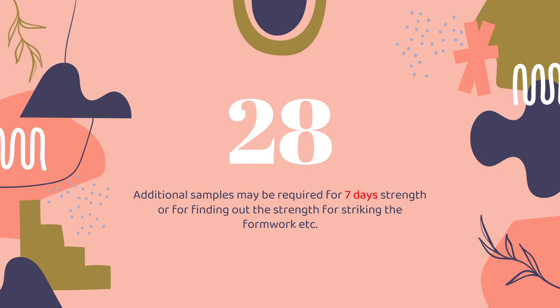Now the next question is: after how many days should we test our concrete cubes? We know we can test after 7 days, 14 days, 28 days, sometimes 21 days also. But the code says you should test your samples after 28 days only. However, if you want to test at 7 days, you can, but for that you have to cast extra cubes beyond those given in the table. This way you can find out the concrete strength and determine when to remove the formwork.